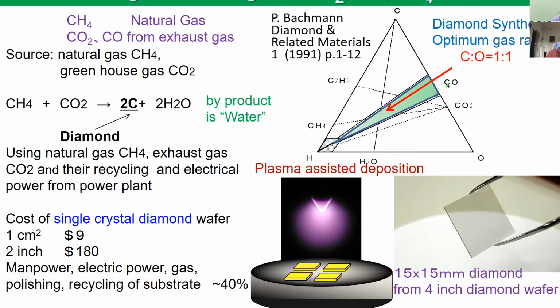Firstly we used carbon monoxide, but carbon monoxide, as you know, is a very toxic gas. So we're using methane and CO2, a mixed gas, and we get carbon, and the byproduct is water. This simple chemical reaction process is very simple, and I like this one very much because methane and CO2 are greenhouse gases, and we get diamond from that. So diamond solidifies those greenhouse gases.